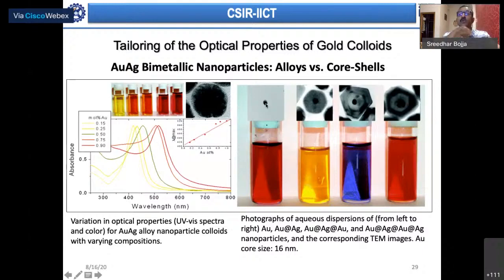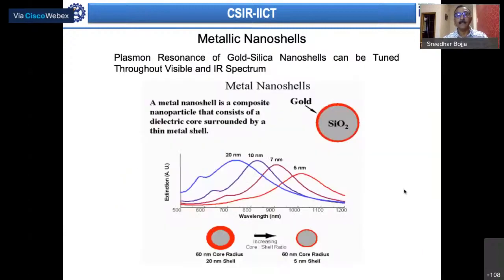When this gold nanoparticle is coated with silver, you see a change in color—completely contrasting, neither red wine nor the color of silver, but yellow, which is completely different. Here it is coated again with gold, and you see blue, which is still more different. Then again coated with silver, and it comes back to its red wine color. This means something is happening, some synergy kind of thing. This is how we start to believe that core shell nanoparticles have properties different from either the core or the shell, something different. This synergy between the core and shell material is what makes these materials so interesting for understanding and usage.